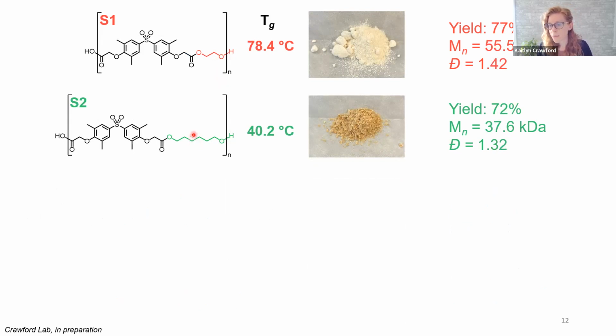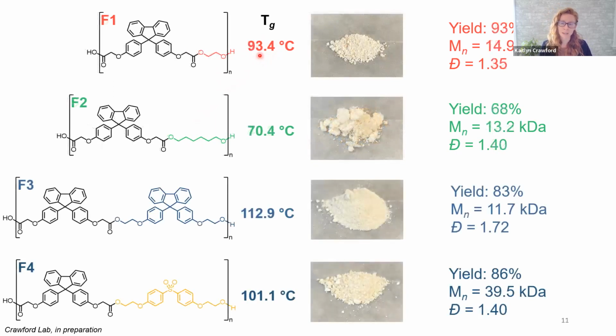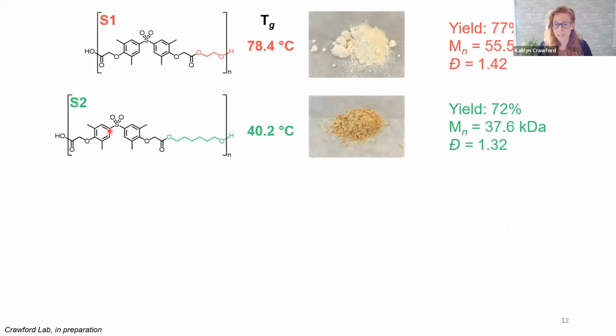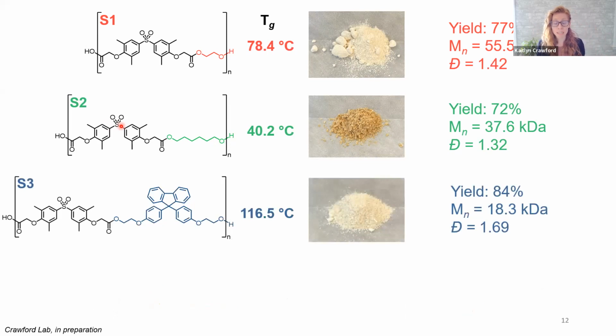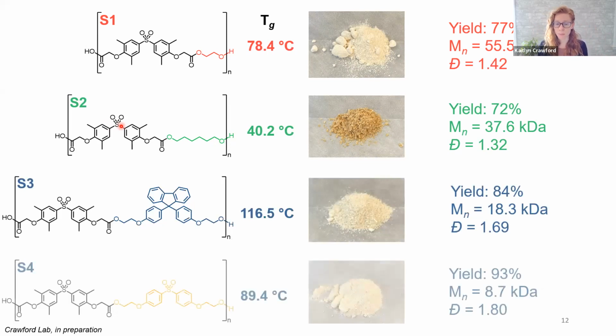And you notice, maybe you noticed, that the glass transition temperature for the sulfone groups is overall smaller, 78 and 40 versus 93 and 70. That's because this sulfone group is less bulky than that fluorene group that restricts backbone flexibility. We did the same thing by pairing the sulfone with the fluorene monomer for acid versus alcohol, and then put the 2 fluorene monomers together as well.